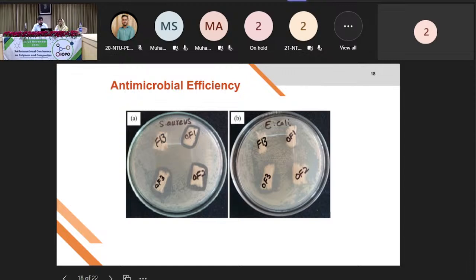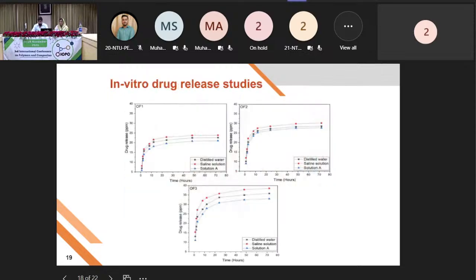The bacterial strain used for the antimicrobial efficacy testing is Staphylococcus aureus. In different solutions, which are distilled water, saline solution, and solution A, our drug is released in a consistent manner, steep at first, and later on, from about 12 hours to about 70 hours, it provides the drug consistently for a long duration.